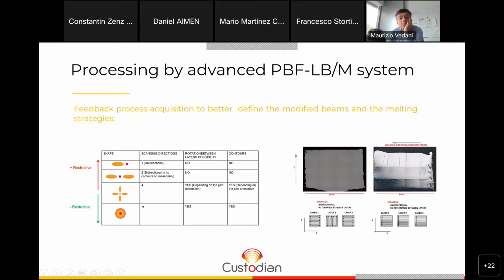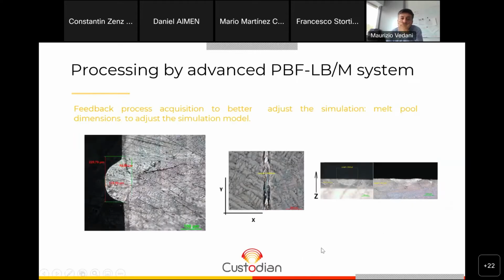And we concluded that bidirectional scan tracks and rotation between layers is mandatory. Otherwise, we can observe that the cracking issue is even worse, and we observe this swelling and this irregular top surface on the part. So that's the reason why we went for a round symmetrical shape, and the one that was proposed for the MPLC. And last, Mauricio, next slide.